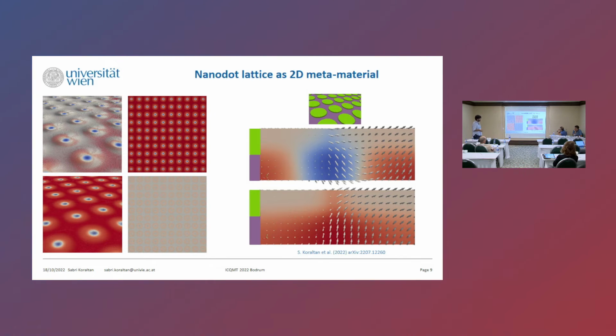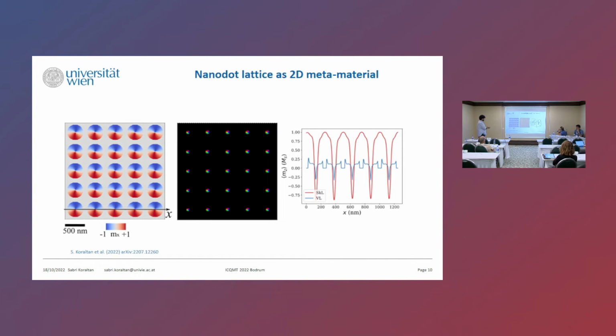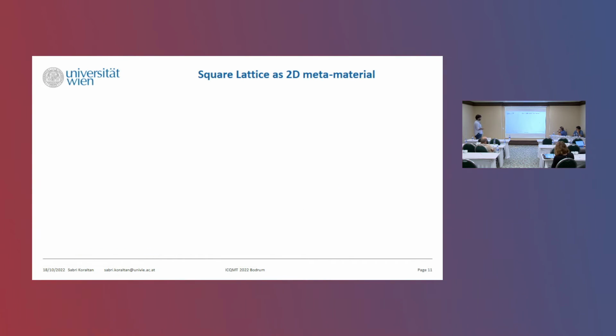In the case where we do not have a skyrmion, then the magnetic vortex core, which points up, is a bit more constant, and only when the skyrmionic layer starts, it starts to diffuse a little bit. Okay, and now one more time, if you plot the magnetization sampled along the x direction, we can see that whenever we have a vortex core which is antipolar to the field, then we obtain the skyrmions underneath. And with the same chirality, as you can see here, they all have the same chirality underneath.